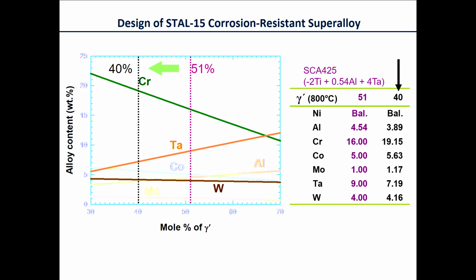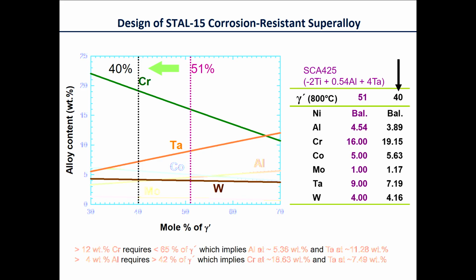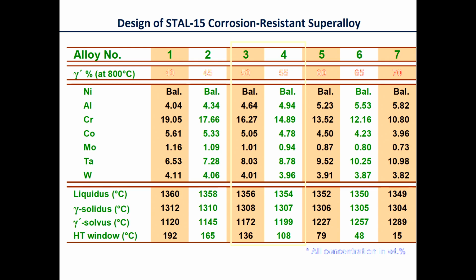And that's why I actually like collaborating with the French people. You have very strong concepts, very strong flair for design. And this is the key point that came from this particular research. And you can see here, taken from maybe 15 years ago, different trial compositions that we came up with on the computer with this idea of the digital twin, modifying the fraction of the phase and its compositions predicted by our thermodynamic